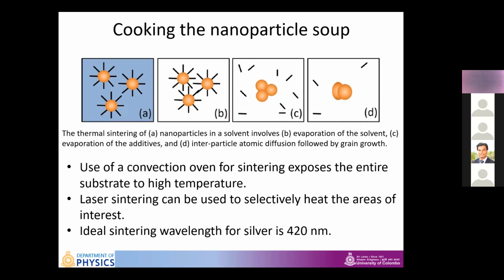Now the nanoparticles can come closer to each other and touch to form conducting traces. Further heating would result in welding of these nanoparticles. Technically, we call this necking or neck formation. In most of the cases, we can use a convection oven, something similar to what you use for baking cakes, to make these inks conductive. Unfortunately, not with heat-sensitive substrates such as paper. That's where a laser comes in handy.